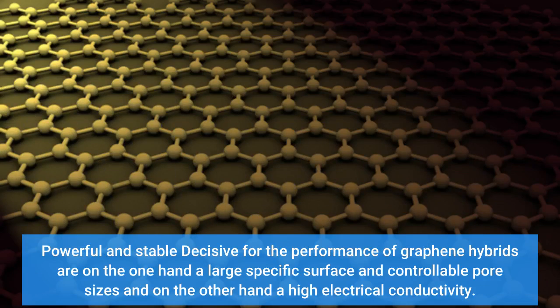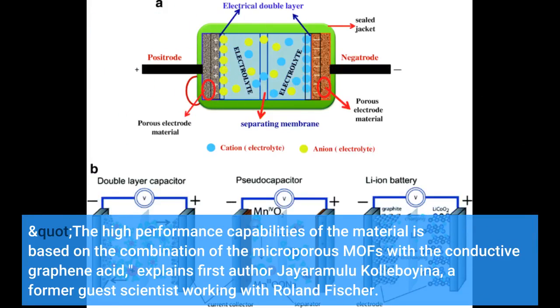Powerful and stable. Decisive for the performance of graphene hybrids are, on the one hand, a large specific surface and controllable pore sizes, and on the other hand, a high electrical conductivity. The high performance capabilities of the material are based on the combination of the microporous MOFs with the conductive graphene acid, explains first author Jayaramulu Kolleboyina, a former guest scientist working with Roland Fischer.